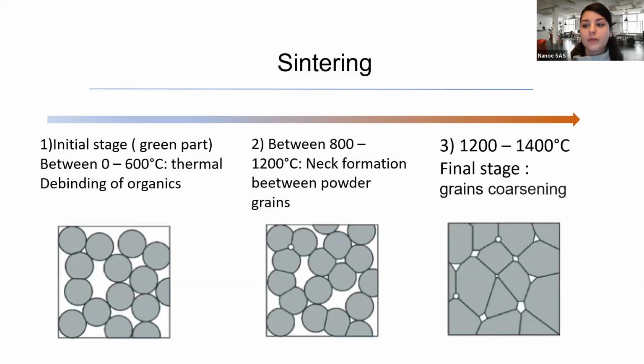The first one, when you put the part in the furnace, the initial stage is when you have a green part. It's like the thermal debinding, when the backbones and the binder are removed. After, the furnace goes up in temperature, up to 1200 degrees Celsius, and there is some neck formation between powder grains, as you can see in the picture. And the final stage, when you reach 1400 degrees Celsius, the grains undergo coarsening and the part will be smaller. So that is what is happening during the sintering process.